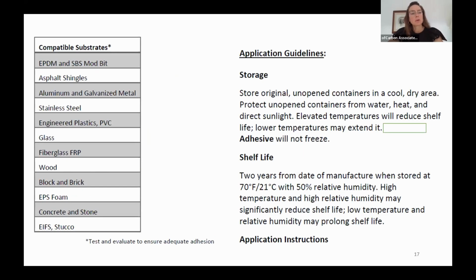The compatible substrates I wanted to also demonstrate, or at least put forward. You'll see stainless steel here. We're doing UL testing, in addition to the others that I just mentioned, on low slope roof decking, because we know we have good adhesion there. We want to get some hard data behind that as well. So a really good shelf life. You'll notice that it is in sausages instead of cartridges. There's a much higher shelf life accordingly, and much less waste when you use a 20-ounce sausage versus a plastic cartridge.